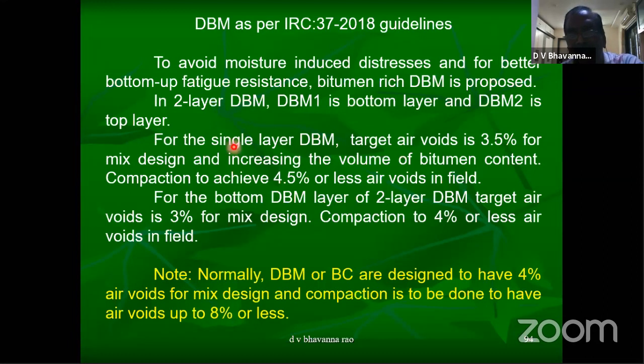If we are going for single layer DBM, target air voids is 3.5% for mix design. Generally, mix air voids permitted is 3 to 5%. They are asking us to go for 3.5% air voids at the time of design if single layer DBM is adopted, and to increase the bitumen content volume more than specified in the MoRTH gradation. Compaction is to be achieved to have 4.5% or less air voids in the field. At the time of design, the air void shall be 3.5%, and after compaction, the air void shall be 4.5% for the single layer DBM.